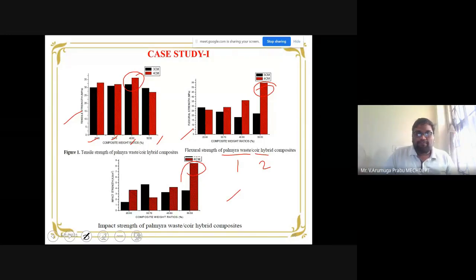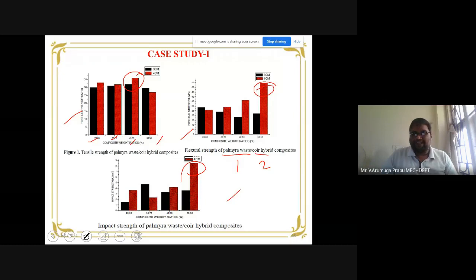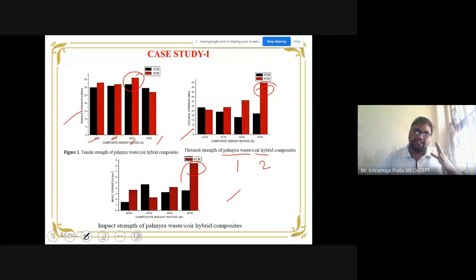Okay. And if you notice, the graph is not in a uniform trend. There is a lot of fluctuation, a lot of deviation in the results. One combination increasing, one combination decreasing, another combination decreasing, another combination increasing. So it makes the researchers think differently. How to think differently now in terms of the manufacturing process, because this kind of result is purely based on the different combinations, different compositions we are using, as well as the defects we can point out in the manufacturing process.